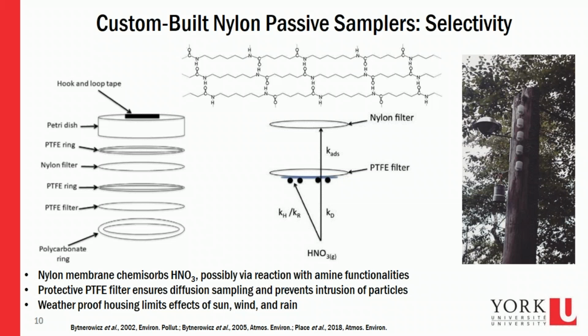surface. So if we have a nylon filter then, and nitric acid can just diffuse to that surface at a constant rate that only depends on its concentration in the gas phase, we can back out over a month what that average concentration in the gas phase is. We can start to parameterize how much nitric acid might be depositing into those ecosystems.